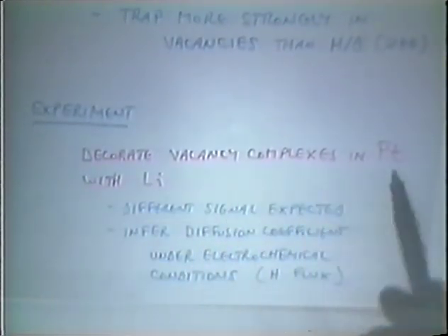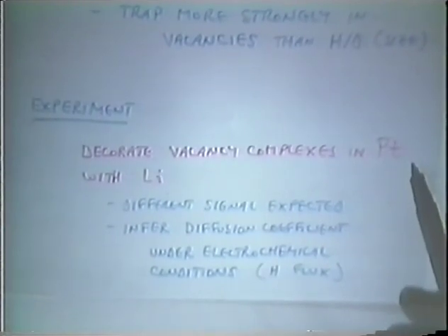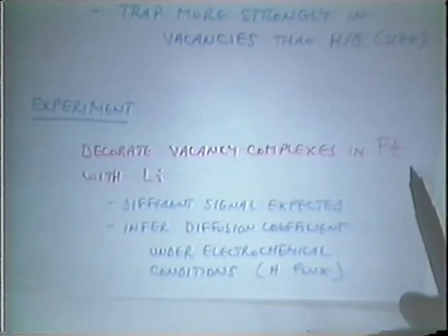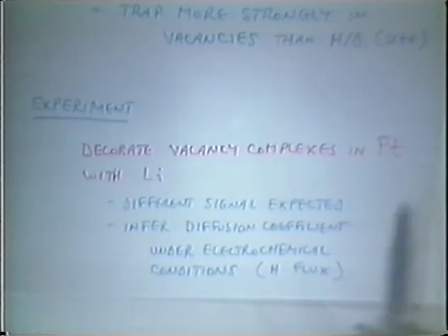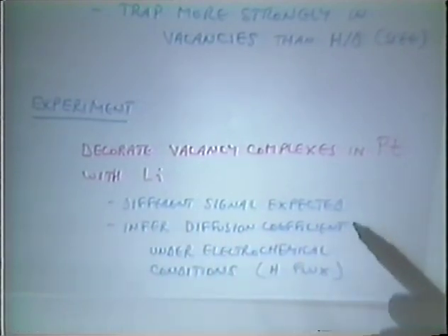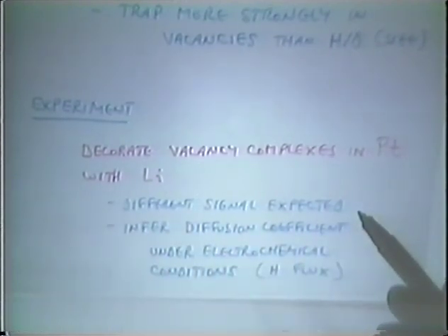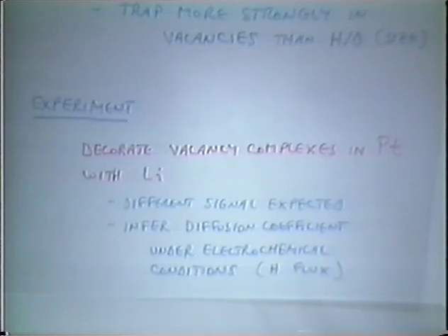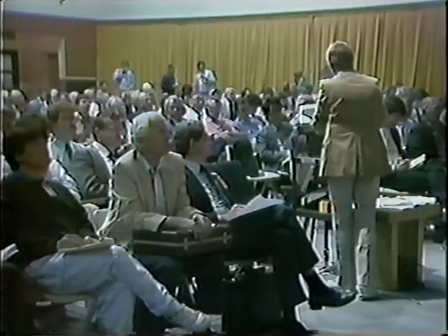So we began an experiment recently to attempt to decorate vacancy complexes in platinum with lithium atoms using this LiOD bath and LiOH. We expected that we would see a different signal for decorating a guest lithium atom, and that we might be able to infer something about the diffusion of lithium into the metal sample under these electrochemical charging conditions, where you have a large hydrogen flux.